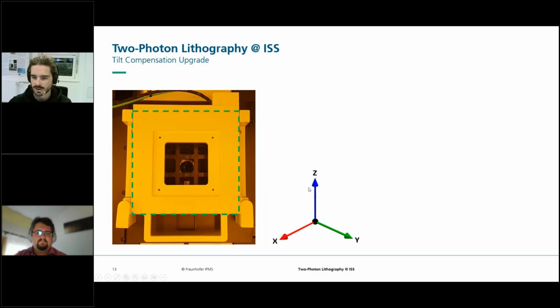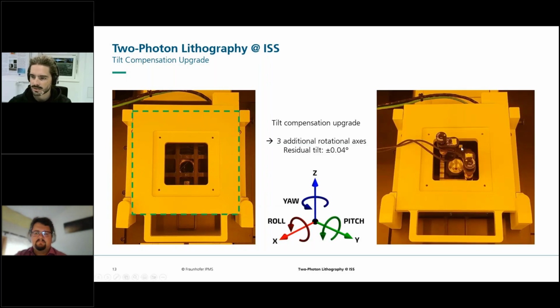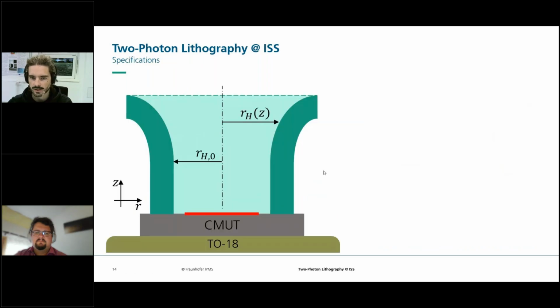Usually we have three axes available by galvo scanner or by piezo stage. With the additional upgrade, this is the system here, we can actually have three additional axes, and the rotational axis. For the residual tilt, I found out that we can go down to very low degrees of tilt, 0.04 degrees actually, and this made it possible to print something on one of our acoustic chips. The acoustic chip here, the CMUT, capacitive micromachined ultrasonic transducer,